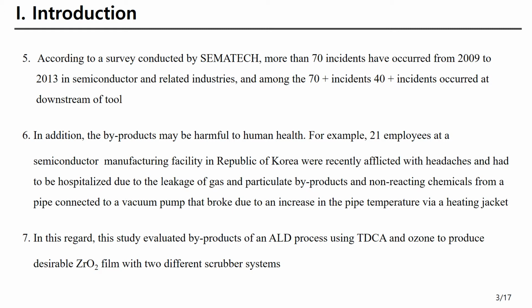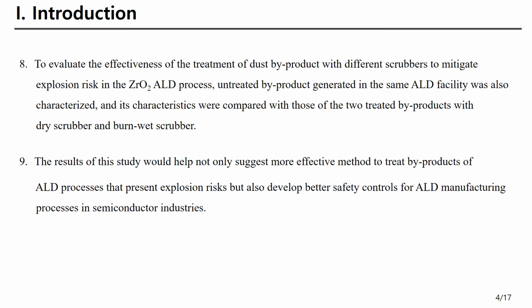In this regard, this study evaluated byproducts of an ALD process using TDCA and ozone to produce desirable zirconium oxide film with two different scrubber systems. To evaluate the effectiveness of the treatment of dust byproduct with different scrubber to mitigate explosion risk in the zirconium oxide ALD process, untreated byproduct generated in the same ALD facility was also characterized, and its characteristics were compared with those of two treated byproducts with dry scrubber and burn-wet scrubber.